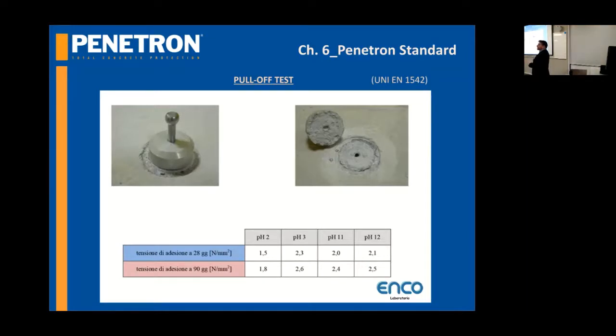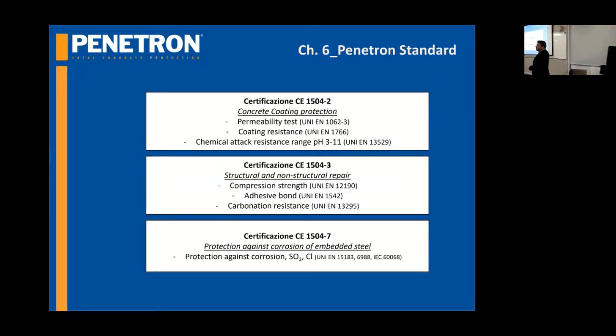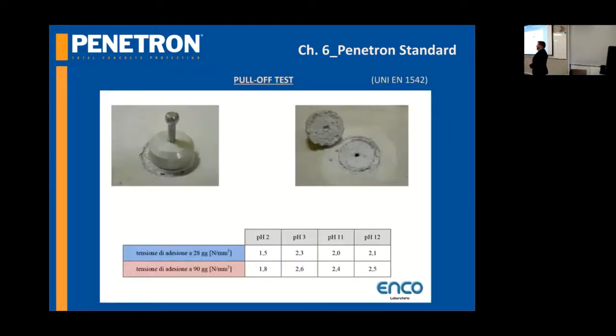Pull-off test. Why is this important? Because, talking about the adhesive bond, one of the main problems when you have to make a repair is to be sure that the mortar or the material you are using could bond with all the support. The pull-off test we did was an aggressive pH test, and we saw that after 28 days we got this value for different pH values from acid to basic. After 90 days, the adhesive tension was higher. So the more time Penetron has to work, the stronger it becomes. The adhesive bond is stronger.